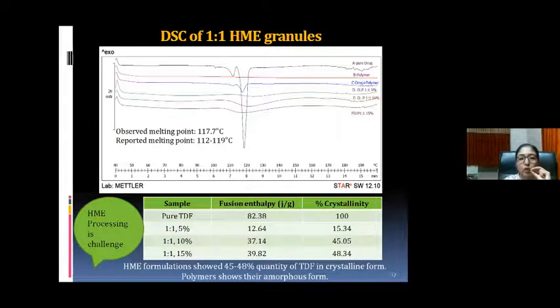Now for the 1:1 ratio, DSC studies were carried out and the percentage crystallinity was calculated. It was observed that the HME formulation showed 45 to 48% of the TDF in the crystalline form, as you can observe over here, and the polymers show their amorphous nature. That is why, in this case, the HME processing will be a challenge.